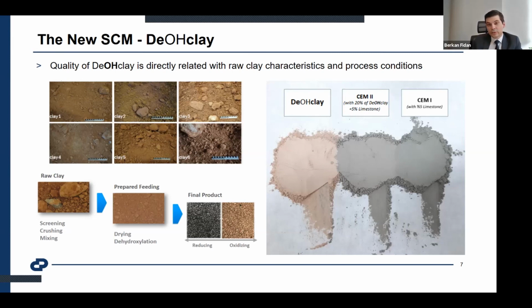On the right side, you can see our actual product in the Abidjan plant. It's dehydroxylated clay. In the current startup and commissioning period, we haven't applied those reducing conditions yet, but we controlled the amount of iron oxide content. That's the reason it's not so reddish. For the cement industry, it's a known color. It's like raw meal color. And the other part is also exactly produced products. As you can see, with 20% added there is not a big effect on the color, and with additional control of reducing conditions, there will not be a problem about the color issue.